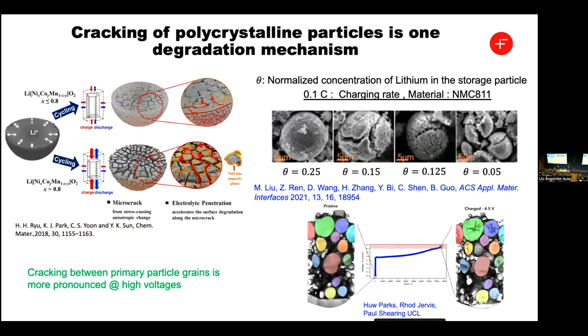So there's been a lot of work. I've already touched on this idea of cracking being important. If you look at a polycrystalline material, inevitably, because of the very large changes in the C parameters, you will get significant cracking between the individual primary particles in your grain. You can see this, and there are multiple studies in the literature. I picked this one here, work done by the UCL group using X-ray CT, and you can see very clearly the development of these cracks, which is much more pronounced if you push to high voltages.